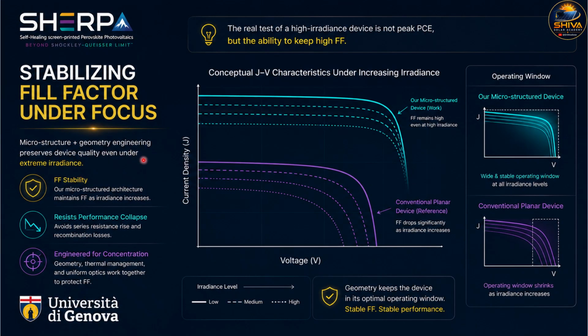So what is the real challenge under concentrated illumination? It is not achieving a high peak efficiency once, it is maintaining a stable fill factor as irradiance increases. In the center graph, the cyan curves represent our microstructure architecture. It is not a real graph, but it can show its properties. Even as light increases, the density of the light rises, the JV profile remains stable and well-shaped. It means that the fill factor is preserved.